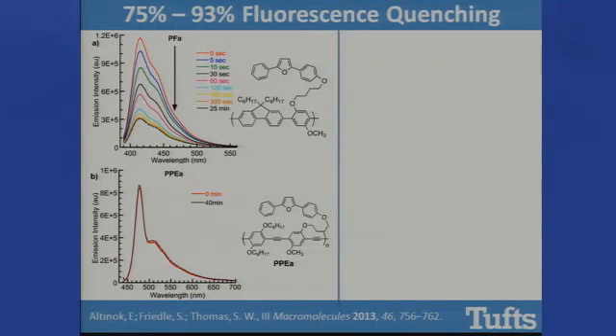So in terms of fluorescence, what do we observe? Well, just as we predicted, we observe a rapid fluorescence quenching of this donor fluorophore, this conjugated polymer. Upon exposure to singlet oxygen, we observe a relatively rapid response that corresponds to the reaction between singlet oxygen and this furan moiety. We see down to about 75%, so a threefold decrease in fluorescence intensity upon reaction of all the furan groups.